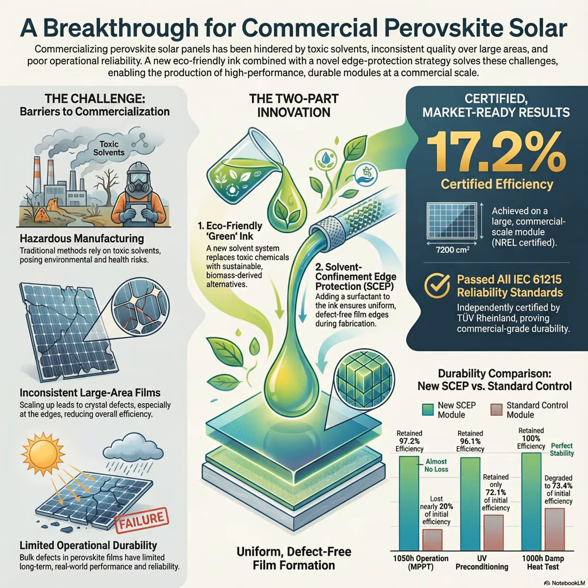They didn't just claim it was efficient. The National Renewable Energy Laboratory, NREL, certified that this large-scale module achieved a total area steady-state efficiency of 17.2%. Why is 17.2% so significant for a module that big? Well, commercial silicon panels today might hit 18 to 20%. But historically, large area perovskites struggled to even reach double digits because of those uniformity problems. Hitting 17.2% on a huge 7,200 square centimeter module proves that this new green manufacturing process works.